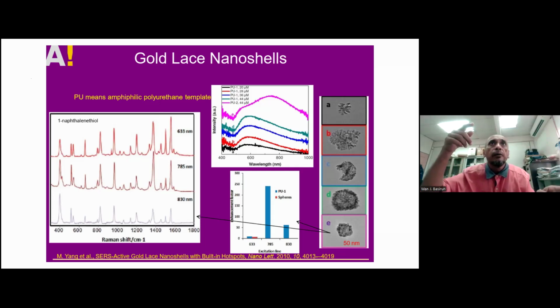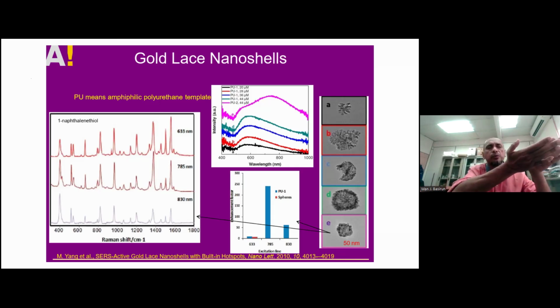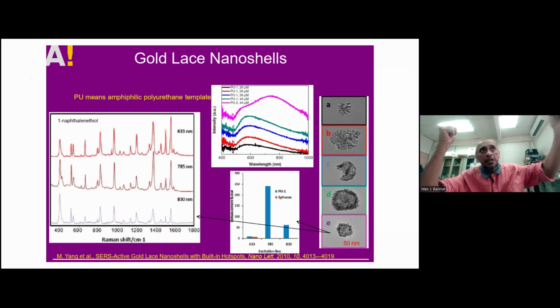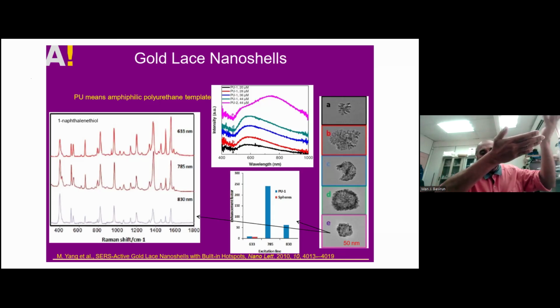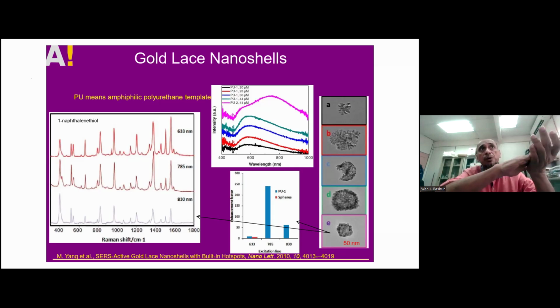As long as the structural or morphological change in the biological sample is due to chemical changes, like the ferrum in the blood getting oxidized to ferrum oxide, then you can observe this in the SERS spectrum, because the ferrum of the fresh blood is not the same as the oxidized ferrum in the blood. Just a simple example: a fresh cow blood is red in color, but when you stain the cow blood onto a substrate, like cotton or a cloth, it becomes brown after days and weeks of exposure, because the ferrum gets oxidized into ferrum 3 oxide, and the color of ferrum 3 oxide is brown. It's just the color of rust.